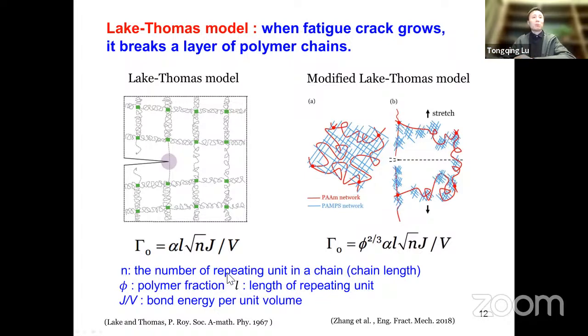N is the number of repeating units, phi is here, and J over V is the bond energy per unit volume. So L times N times J over V is the energy to break a layer of polymer chains. Here N has a factor of the power of 1 over 2, 0.5. There's a theoretical derivation. So this is the traditional Lake-Thomas model to predict the fatigue threshold of rubber.